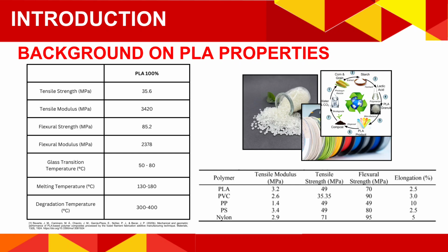To put PLA into perspective, we compared it with other common polymers. While PLA has a higher tensile modulus than PVC and PP, it has relatively lower elongation at break, meaning it is more brittle. Compared to nylon, which has a flexural strength of 95 megapascal, PLA is stiffer but less flexible. These characteristics highlight the need for modification to improve PLA's flexibility while maintaining strength, which is the focus of our study.